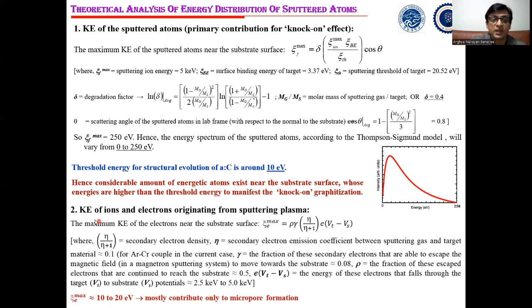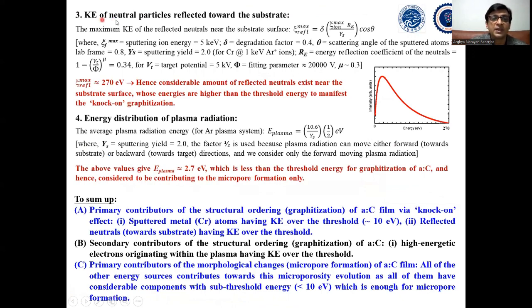Similarly, we did the theoretical analysis of the kinetic energy of ions and electrons originating from sputtering plasma, and we see that the energy is varying from 10 to 20 electron volt. So it is not contributing too much for the structural ordering, but mostly contributes only to the micropore formation. Similarly, we did the theoretical analysis of the kinetic energy of neutral particles reflected towards the substrate. Here also we have observed that the energy is varying from almost 0 to 270 electron volts. So a considerable amount of reflected neutrals exist near the substrate surface whose energies are higher than the threshold energy to manifest the knock-on graphitization.